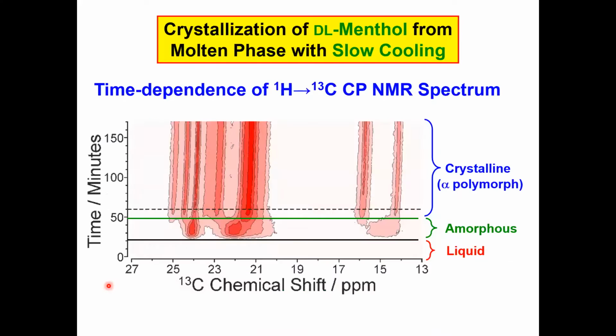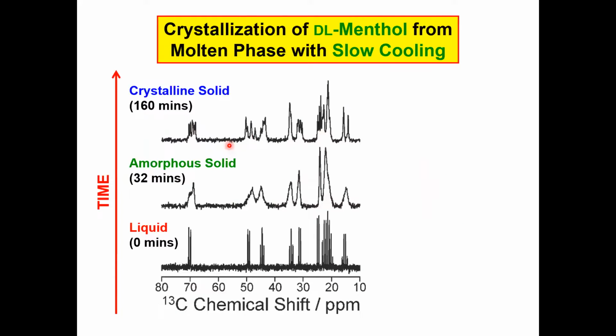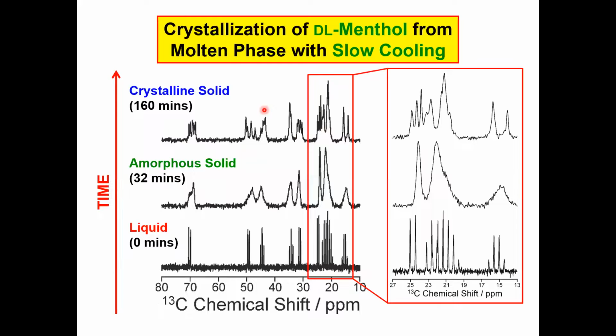at that time. But if we zoom in more detail on the solid-state NMR spectra, we can see that at the beginning, we have very, very broad lines as shown there, right? And that's characteristic of an amorphous phase, which then crystallizes subsequently at this point to give much sharper lines in the spectra. And here are representative spectra shown, the liquid phase, the amorphous phase, and the crystalline phase. So clearly, initially there is formation of the amorphous phase, and then the crystallization happens from the amorphous phase, as shown there.